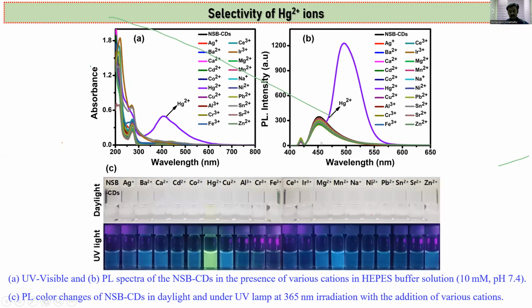After addition of the different metal ions, we didn't get any fluorescence intensity changes, very little and very low. Then with the addition of mercury ions, we can get the highest intensities, a threefold increase. We can see clearly from this one, at 450 nanometer, and then with the addition of mercury ions it shifts to 496 nanometer. We can also clearly see the blue emission turns to green emission with the addition of mercury ions.